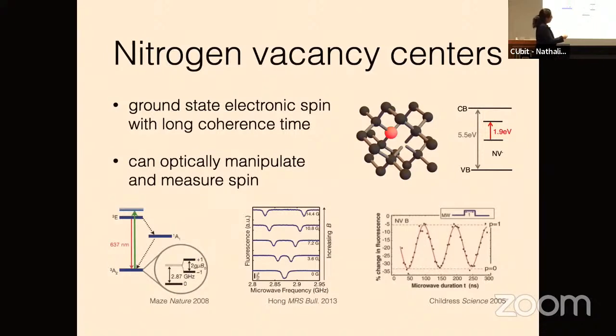And then you can do coherent manipulation of this ground state and then this optical readout to figure out what it is that you've done. And then importantly, because you're in diamond, which has very low density of states for phonons, it's a very stiff lattice, and these are all very light atoms, you can actually have a very, very long spin lifetime even at room temperature. So at room temperature, the NV center has a T1 of something like 10 milliseconds.